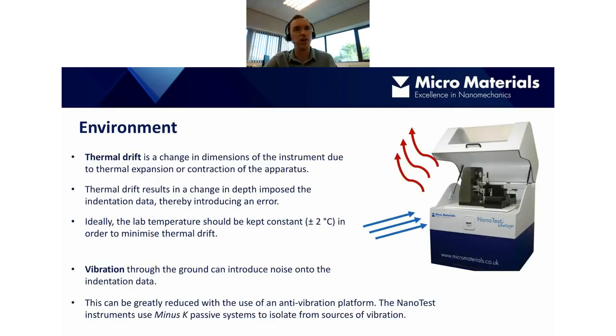So first of all, we go back to the environmental considerations. The thermal drift is essentially a change in the dimensions of the instrument due to thermal expansion or contraction of the instrument itself. Okay, so if the nano indenter is situated in a location where there isn't really any temperature control, then we will often see what's called thermal drift on our measurements, which is essentially a change in depth imposed on the indentation data due to this contraction or expansion. So basically, it's an error which we need to try to eliminate or minimize as best we can.